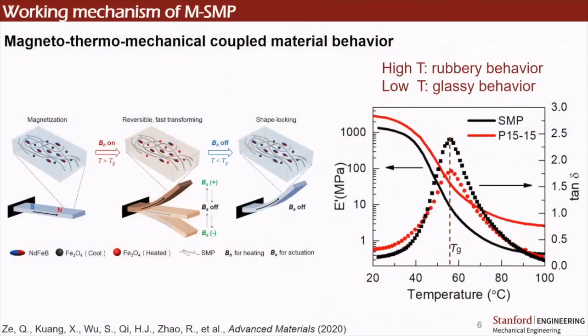To introduce this new composite, called magnetic shape memory polymer, basically this is a multi-physics material. It couples magnetic behavior, thermal behavior, and also shape morphing, which is the mechanical part. We embed two types of magnetic particles. One is the hard magnetic particle, neodymium iron boron, which is in charge of shape morphing, and the other is iron oxide. We embed these two particles in shape memory polymer, which is a material that can change its rigidity under temperature change.